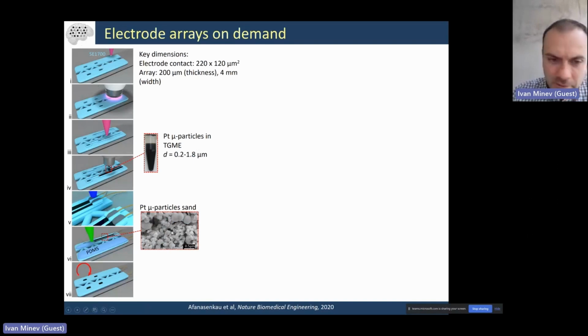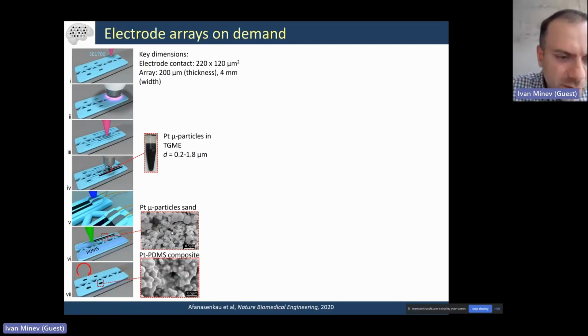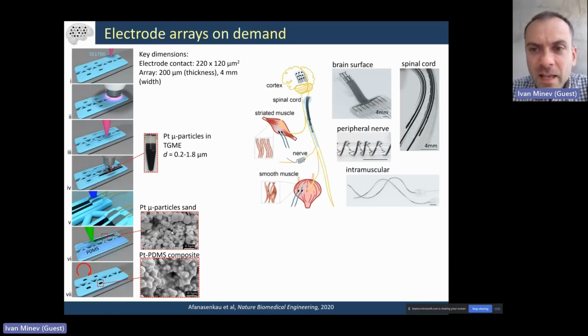And then we can flood this with extra silicone, which penetrates in between the particles and creates a composite material in situ that is blended with the rest of the silicone components of the device. It has electrical conductivity but survives mechanical stretch because it is a composite. And we use this to produce a library of electrode arrays that could be easily changed in terms of where the individual electrodes are placed.